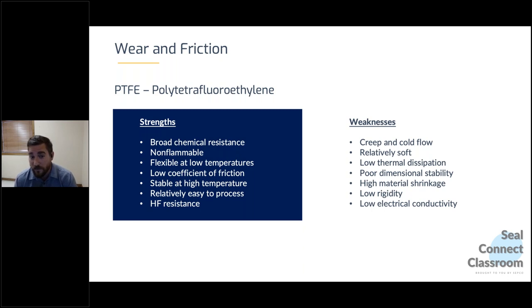The weird temperature for PTFE is about 78 degrees, at which it actually starts doing weird things. At or below room temperature, it holds very true. But above 78 to 80 degrees, it starts thermally expanding, and it does so up until its glass transition temperature, say 300-ish, and then it's good to 550 continuous. But PTFE moves almost instantly above room temperature. We're talking about small dimensional changes, but depending on your diameter, PTFE moves almost immediately as far as temperature is concerned, which is why we add fillers to it. I hope that answers your question, but PTFE moves a lot and at very low temperatures.